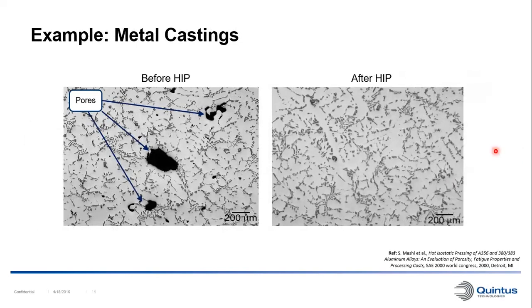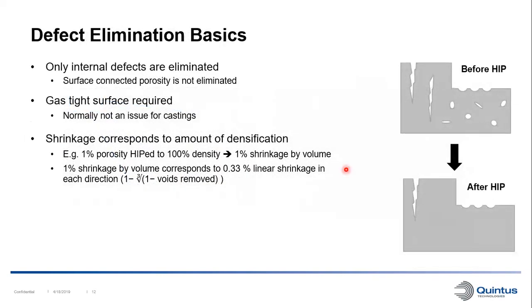Here's an example of a real casting porosity microstructure. So here we can see some typical casting porosity, and these type of defects can also be eliminated by the hip process. One thing to notice is that it is only the internal defects that are eliminated with the hip process. Any surface connected feature where the pressure media can penetrate will not be affected by the hip. So for example, a surface crack like this, the pressure media will just go into the crack and there will be no net force to close that crack. Also, a rough surface will not be affected by the hip process. So a gas-tight surface of the component is a requirement for hipping, and this is normally not an issue for castings, which is a good thing.